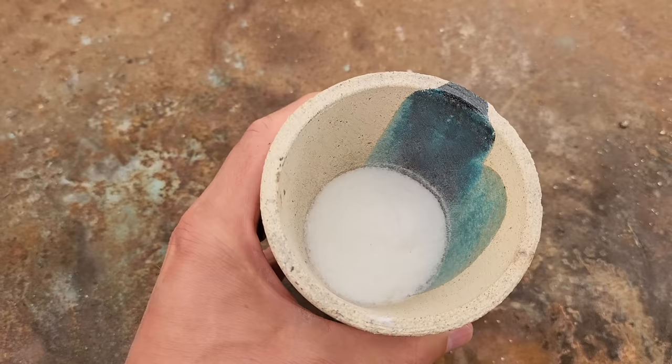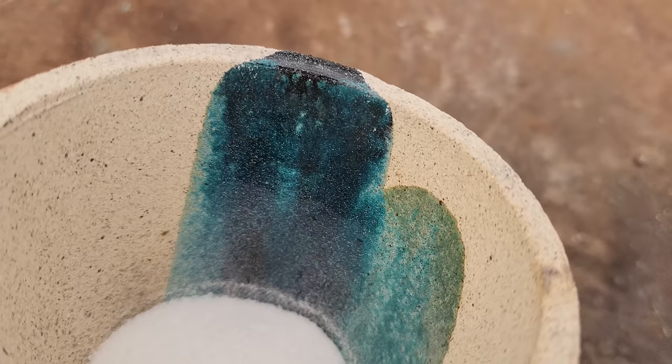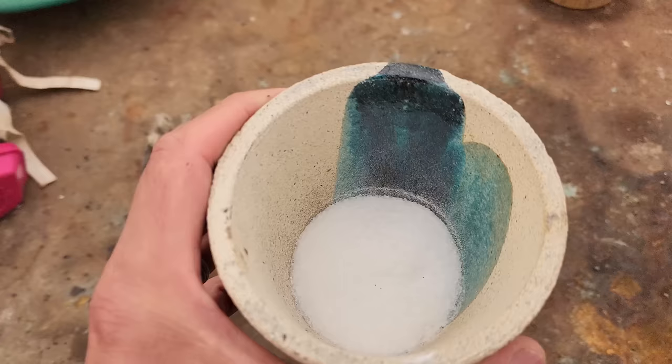The next step is to take our silver button and cemented silver, which is in the bottom of this crucible. This is the one I used the other day. And look at how pretty blue that flux is, that slag. But now I'm gonna melt this down in the furnace, pour it into our cone mold. I've used quite a bit of borax and I've added a little bit of potassium nitrate to try and oxidize off some of that last little base metals that's in there. We'll pour it into our cone mold and then we can see how pure our silver is.